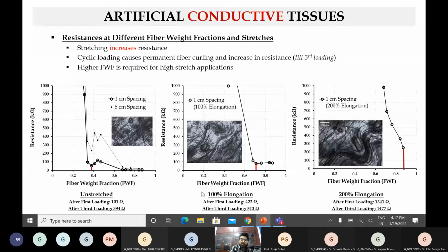The first deal was, we want to look at how we can optimize this resistance so that current actually flows. The next step, now that we have optimized the resistance, is how do we tune the mechanical properties? So these were two steps. As a first step, we narrowed down that at close to 0.4 fiber weight fraction, by weight in this case, the resistance falls drastically. This is the resistance plot going down, and this is where it falls below 100 kilo ohms. We understood that this is a reasonable number for passage of electricity. So we thought this could be a good starting point: if the fiber weight fraction is around 0.4, that is good for this.